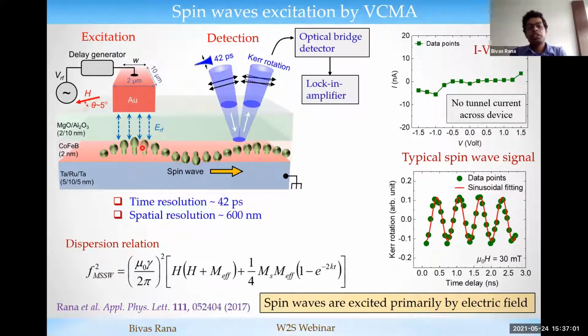And if it satisfies the resonance condition, then the spin waves are excited and propagate in both directions. For the detection, we use a picosecond laser beam with a pulse width of around 42 picoseconds, and we use the Kerr rotation from the reflected beam of the system. This Kerr rotation is proportional to the amplitude of the spin wave. To measure the Kerr rotation, we use a specially designed detector called an optical bridge detector, connected to the lock-in amplifier.